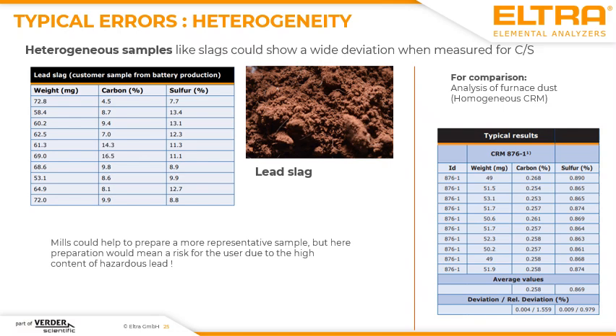When you are starting with analyzing a powder, you maybe get very irritating results. Here on the left side, for example, you see typical results of a lead slag, which is, I would say, a waste product of battery production. And here you see that we have a very strong deviation in the carbon results, which, for example, starts with 4.5% and goes even up to